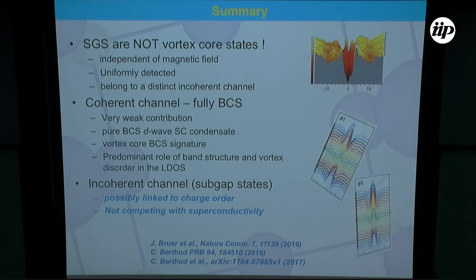And we see that by modeling the vortex distribution and comparing with the data, we can really extract this zero bias anomaly which is expected in the case of a D-wave superconductor. Now finally, we might link these subgap states with the charge order, which would imply in that case that this charge order is not competing with superconductivity. These are the references you can read, which is actually a summary of all this talk. Thank you for your attention.